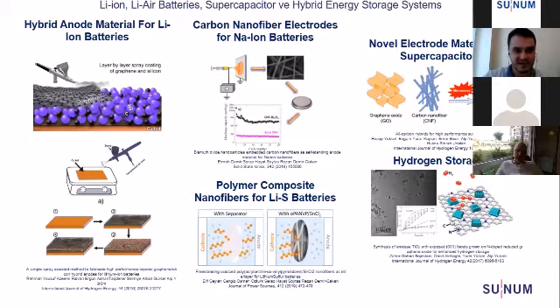These are examples that have been studied in our infrastructure by our researchers. In the left one, a hybrid anode material was produced for lithium-ion batteries. The surface of the graphene is coated with silicon nanoparticles, and then sandwich-like structures were produced and used as hybrid anode material in lithium-ion batteries. And very successful results were obtained with that system.